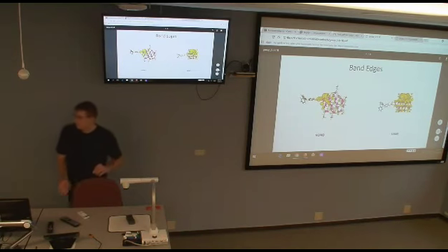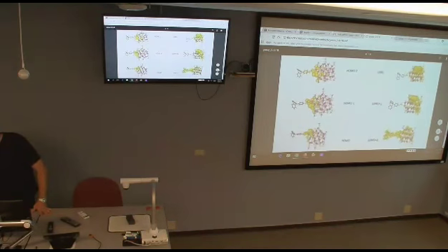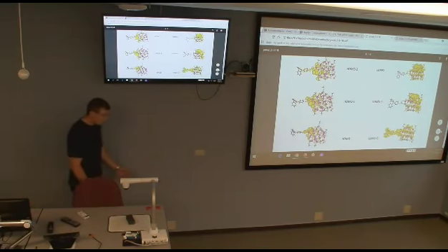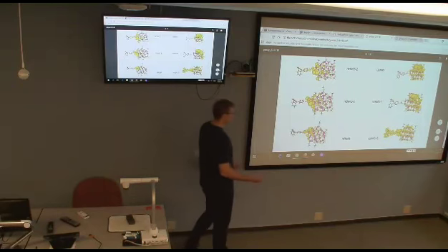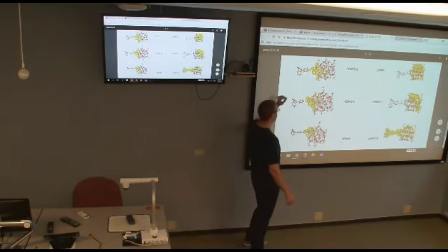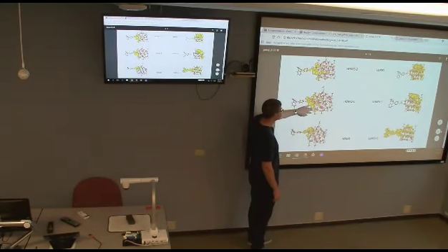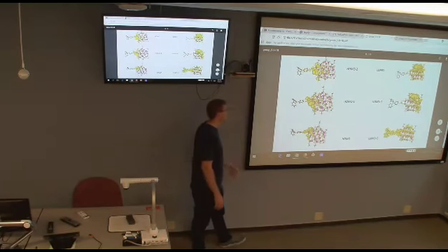Okay. So the other thing that I want to highlight are similarities and differences in some of the orbitals around the band edges compared to the carboxylic linker. This is what I showed you, the HOMO and LUMO on the previous slide. Looking at the edge of the valence band, you can see that again they're going to be more localized around this linker group, but also going a little bit deeper, you see a little more delocalization across some of this organic piece.